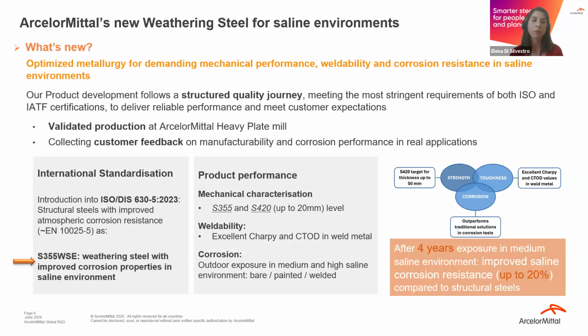So where are we now? We validated the production of this product at our ArcelorMittal heavy plate mill. So we had industrial production. We tested the product performance in terms of mechanical characterization. So we targeted an S355 value in terms of mechanical strength, but we also tested the S420 for the moment, up to 20 millimeter plate thickness, but we could achieve even higher thicknesses if required. We tested weldability, of course, and we got excellent Charpy and CTOD in weld material.